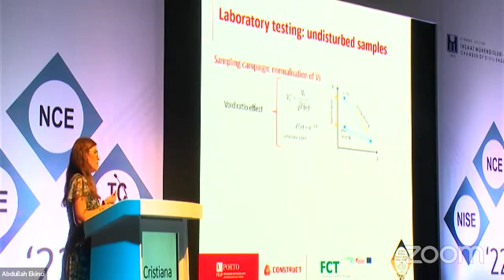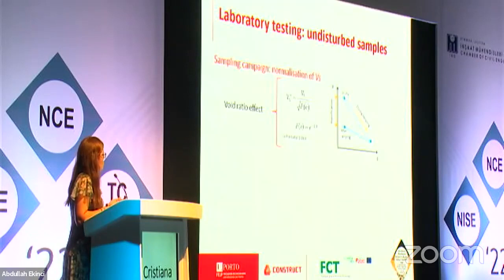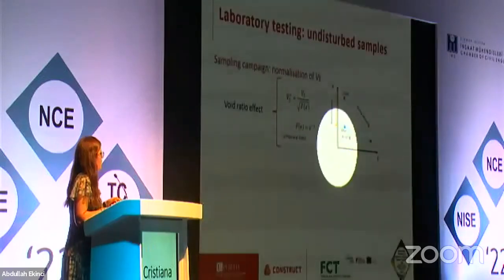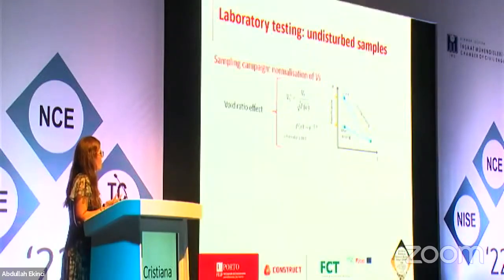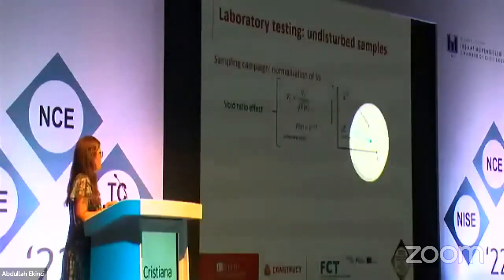And this is very important. When you're comparing shear wave velocities in the field with those in the laboratory, you cannot do the comparison directly because there is a change in void ratio that we need to take into account. Otherwise, the comparison may be invalid. So when we have an in situ condition and we extrude the sample to the surface, we have a change in effective stress, and we need to account for that. And after sampling, you can see here that the sample is moved somewhere here. When we load it in the laboratory to the in situ condition, then we get to here, right?